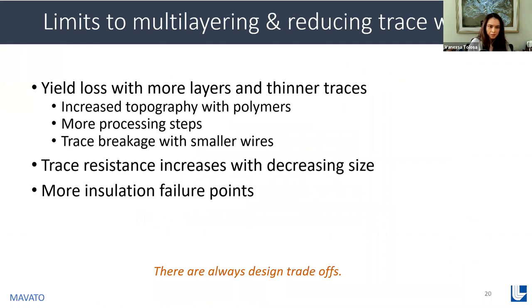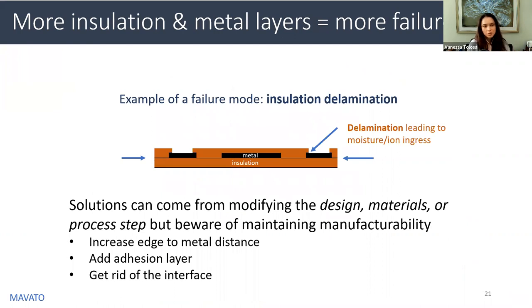So here I've summarized the limits that I just talked about. The only thing I haven't mentioned is that as you increase more layers, you're also creating more insulation failure points. And that's because one well-known failure mode of polymer devices is delamination. So you can get ion ingress from these salty, wet environments of the body, and when that happens, eventually your metal traces and your electrodes will short and corrode, and you lose functionality of your device. So I don't have time to go into this failure mode in detail, but it's an important note to make anytime you're talking about challenges in high channel count polymer-based microfabricated probes.